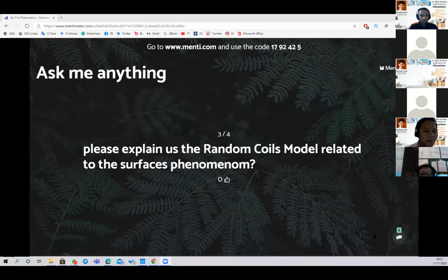Of course, in the bulk, polymer chains should have a random coil conformation, but at the surface and at the interface, polymer chains cannot take those conformations. Then polymer chains should have a so-called pancake conformation, and the actual chain is pretty much compressed along the D direction. In that case, of course, the chain must lose conformational entropy. So the dynamics of polymer chains at the surface and interface are different from those in the bulk. This is a very important question and a very good question.